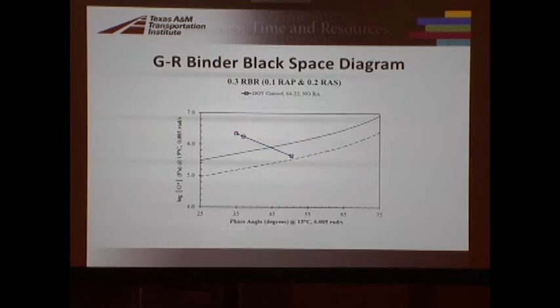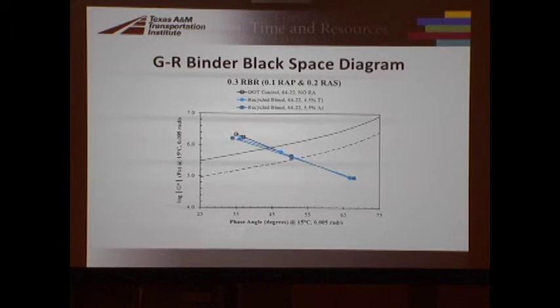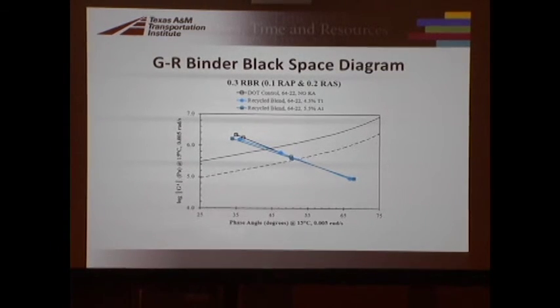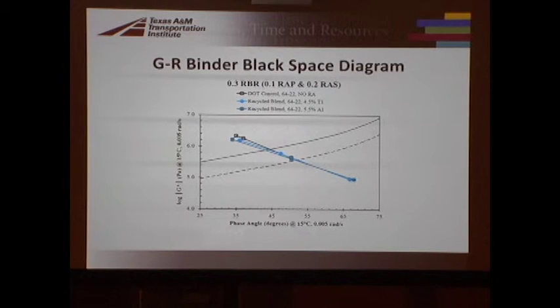So you'll see that, look what happens when we put the recycling agents in there. Oh, that's great. It goes back down and toward the right. So that's good, and that's what we want. But what happens with aging is that it's still out here past these cracking thresholds. And these are very loosely based on those airport pavements, but still there's some kind of threshold. So it's not good with aging.